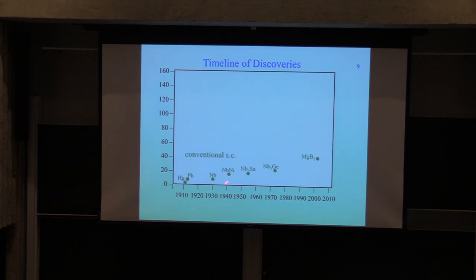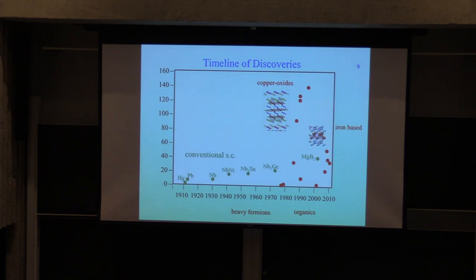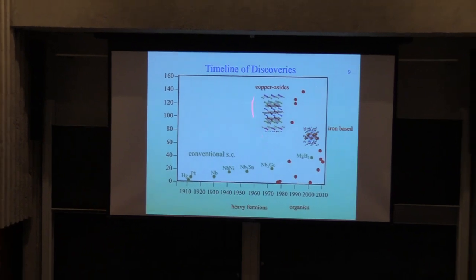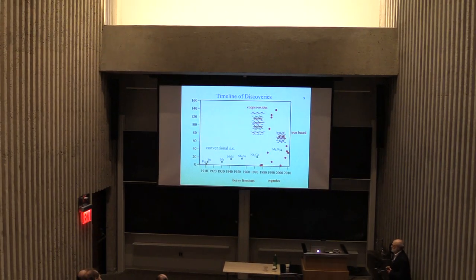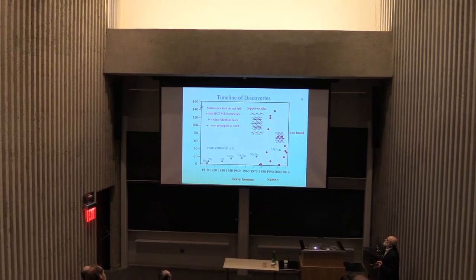But again, this was good for searching and finding these materials, but it was not good for finding many other things. And the field of strongly correlated electrons really started to take off when people started to discover materials that were not like the ones that Matthias worked on. In particular, there was a big breakthrough with copper oxide superconductivity, which really broke the slope in the TC versus time. And more recently, there are some iron pnictide materials which are also high temperature superconductors, and depending on my time, I'll tell you a little bit about those. So those materials don't fall within this framework of Landau Fermi liquid theory plus density functional theory plus perturbative corrections, and those are the strongly correlated materials. And there are materials that don't obey Matthias' rules, they don't obey the BCS theory, and there are probably new principles at work.